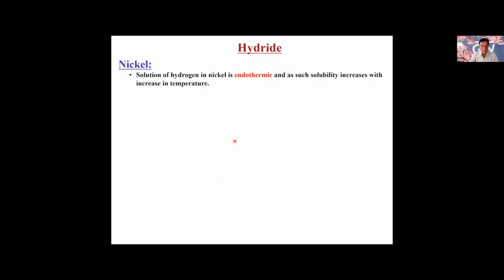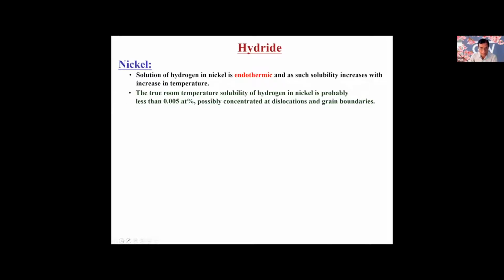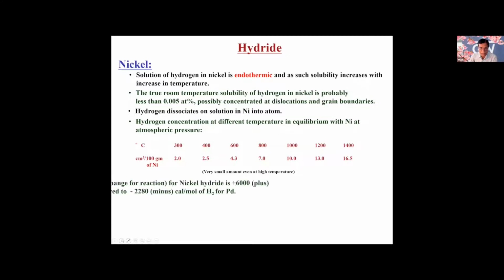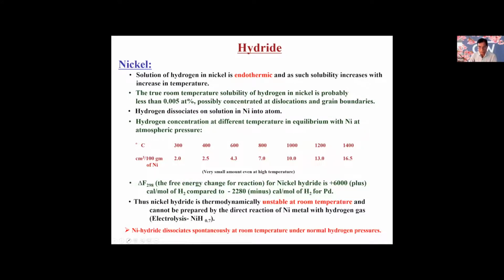Now moving forward about the nickel, because nickel has become very important because a lot of positive results have come out. So nickel, one thing here, is that hydrogen going into nickel is endothermic, and solubility increases with temperature. And just to give you some idea about the nickel here, you can see that the solubility is very, very small. So the main thing I wanted to mention here is that nickel hydride dissociates spontaneously at room temperature under normal hydrogen pressure. And the room temperature solubility is very low. So that's the main message I wanted to give here.